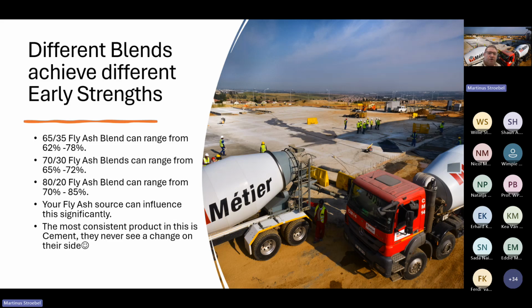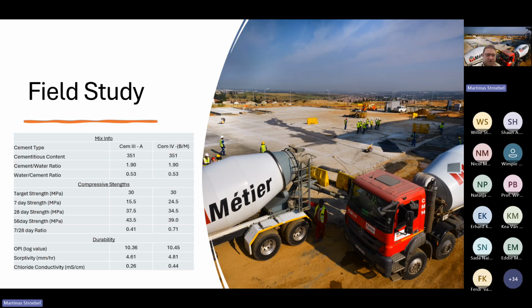Yet the concrete is not of bad quality, even though concrete is 9 out of 10 times being blamed for poor quality if it doesn't meet the expectation initially. So we did a field study, and this is courtesy of Giselle in Durban. We ran comparisons between a CEM III-A and a CEM IV-B/M, blended at the same cement water ratios, and I think the extension, if I remember correctly, was about 50-50 clinker versus extended. Both had target strengths of 30 MPa.